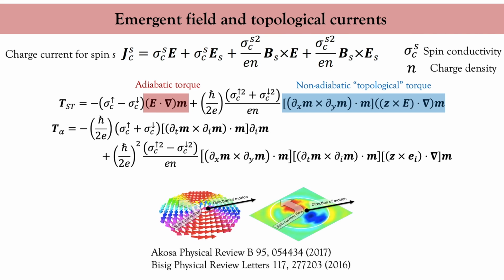We proposed this torque a few years ago, and at that time, we were collaborating with the group of Matthias Kläui to understand the reason why the non-adiabaticity was severely enhanced in magnetic vortices. As we understand it, this torque comes from the presence of a spin Hall current induced by the non-trivial topology, which induces a local non-adiabatic torque on the vortex. In addition, this torque is proportional to the gradient square, so it increases when we reduce the size of the magnetic object.